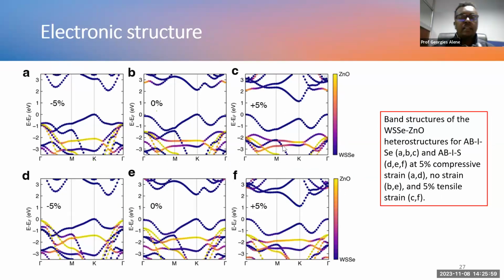Then we investigated the electronic structure of the system. In the middle, in B and E, you can see the two selected heterostructures without applying any strain. And we also investigated applying tensile strain, as shown in C and F, 5% tensile strain. And we also studied applying a compressive strain, like negative 5%, for the two systems. So when we see the electronic structure, the conduction band minimum and the valence band maximum are contributed by the WSSe. So the zinc oxide actually has no effect on the band edge contributions, but it is dominated by WSSe.